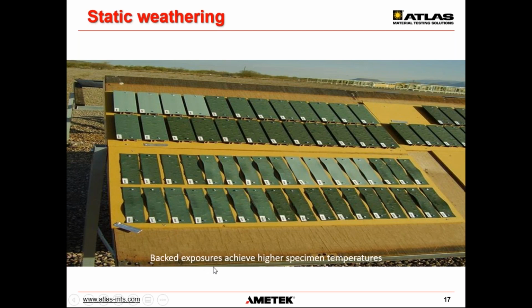Backed exposures typically will always have a higher specimen temperature than unbacked exposures, because with unbacked exposures you get a little more cooling from any sort of airflow, wind that is blowing in and around the racks. And so this can be very important for looking at different types of degradation.